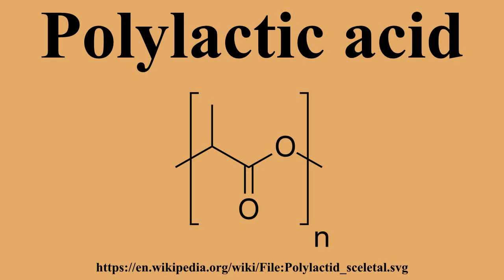Chemical and physical properties. Due to the chiral nature of lactic acid, several distinct forms of polylactide exist. Poly-L-lactide is the product resulting from polymerization of L,L-lactide. PLLA has a crystallinity of around 37%, a glass transition temperature of 60 to 65 degrees Celsius, a melting temperature of 173 to 178 degrees Celsius, and a tensile modulus of 2.7 to 16 gigapascals. Heat-resistant PLA can withstand temperatures of 110 degrees Celsius.